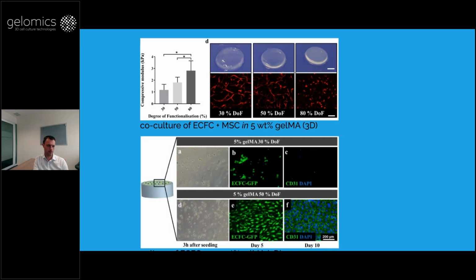But then when we culture HUVEC, so endothelial cells on top of gelMA, it shouldn't be too soft because then they don't adhere, they let loose. So you need a minimum stiffness. So we found this sweet spot here, the 50% DOF, 2 kilopascal stiffness, that supported both capillary formation inside as well as a monolayer of endothelial cells on the surface.